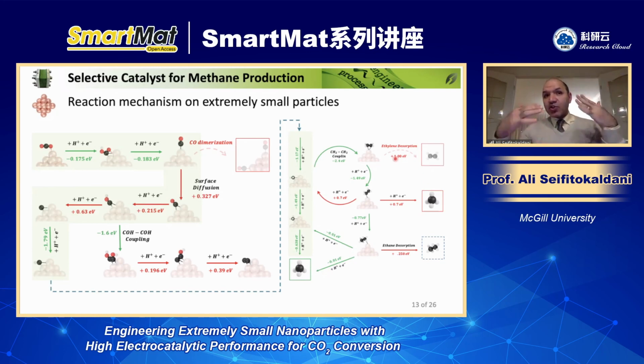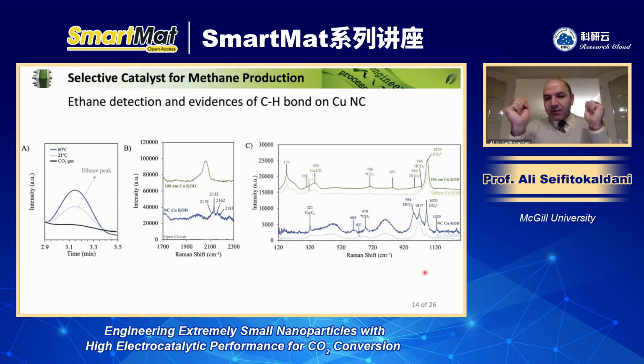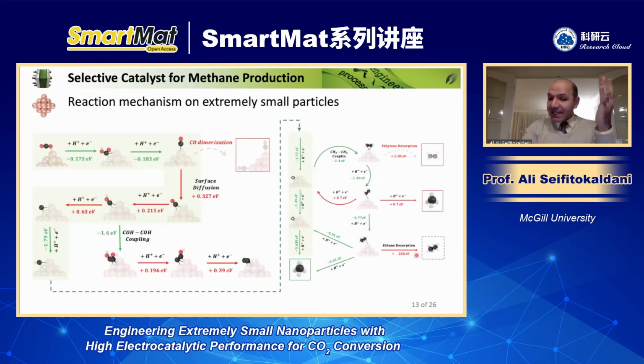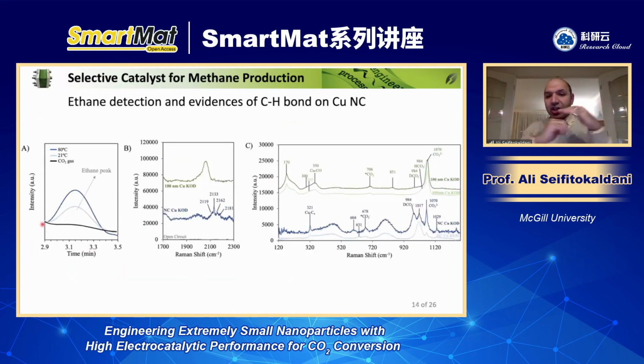Which is not the case when you use, in fact, the copper supported on carbon in many papers, including some of my own research papers published previously. And also we expect to observe some ethane. So to further investigate this hypothesis, we were curious about detecting ethane, because we said ethane is something that we may expect, but not ethylene. And then we calibrated carefully our gas chromatography, and then we observed the ethane peak on extremely small particles, like on 1 nanometer particle or 0.5 nanometer particle.